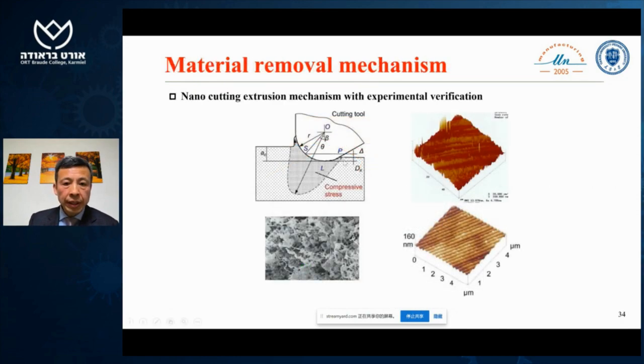And also based on this kind of development, we can generate nanometric surface on brittle materials. You can see here, conventionally, if we cut brittle materials, there is a fracture on the surface. If we can understand the material removal mechanism, we can achieve the surface without fractures and cracks. And if we look at the chip, you can see the chip is a continuous chip for brittle materials. That means we are cutting material in a kind of ductile mode.